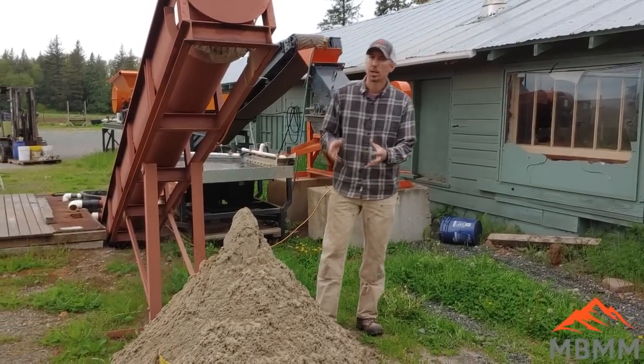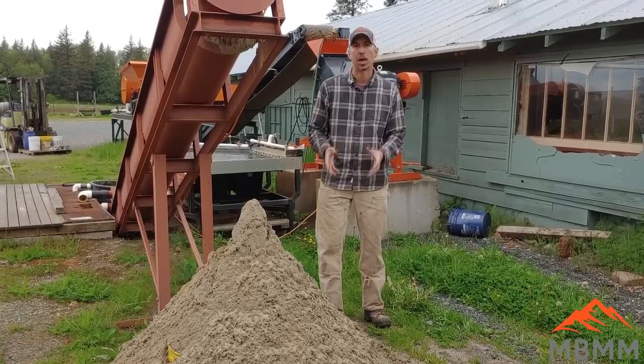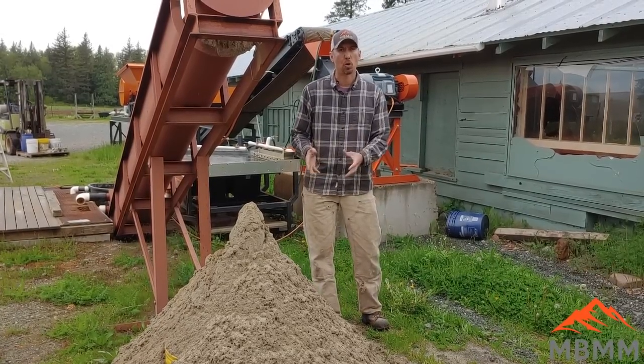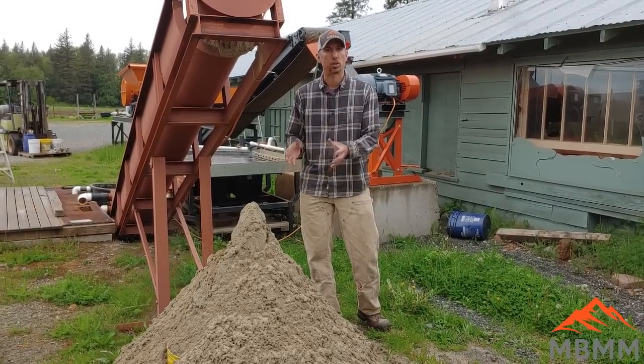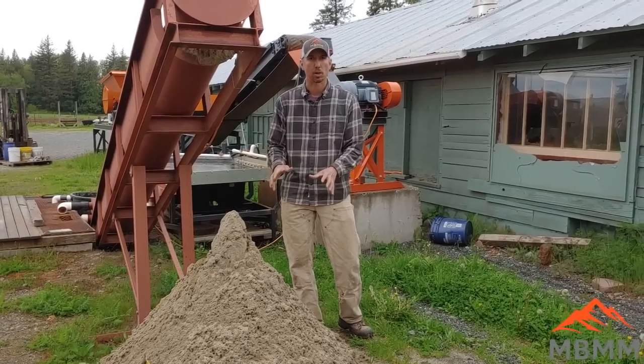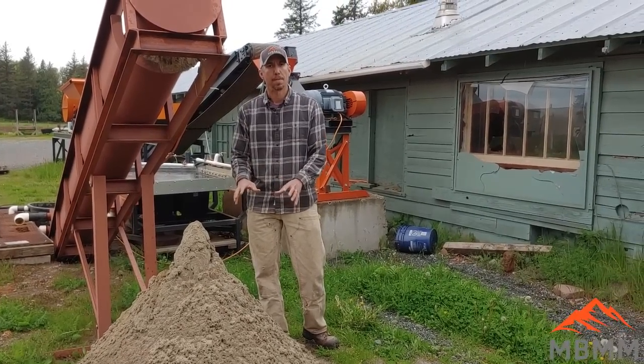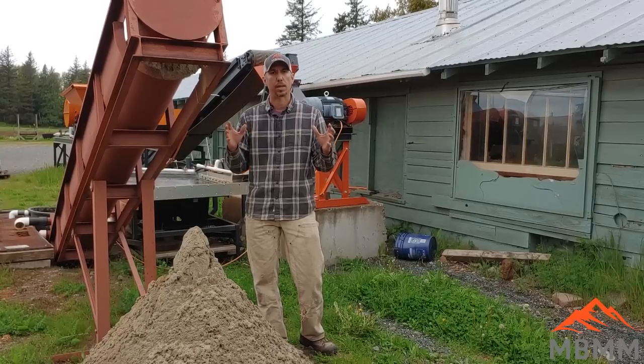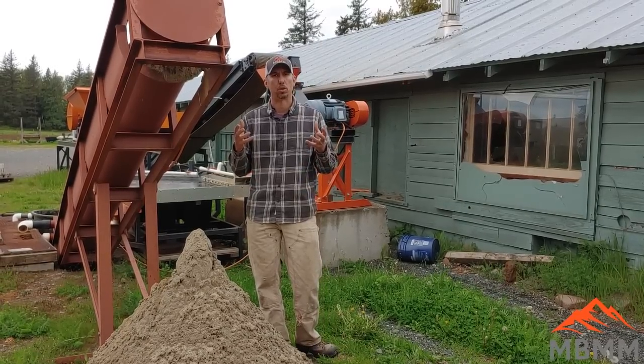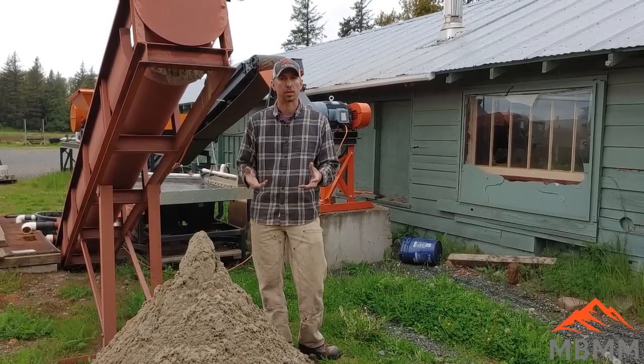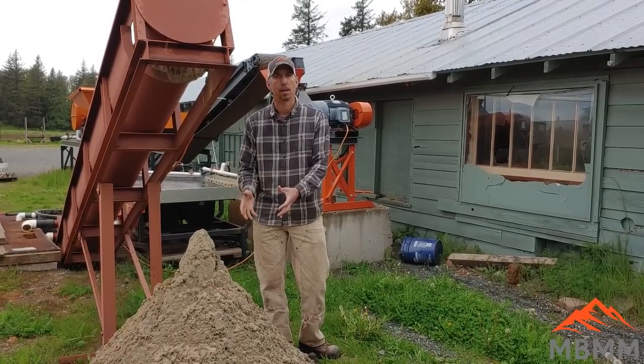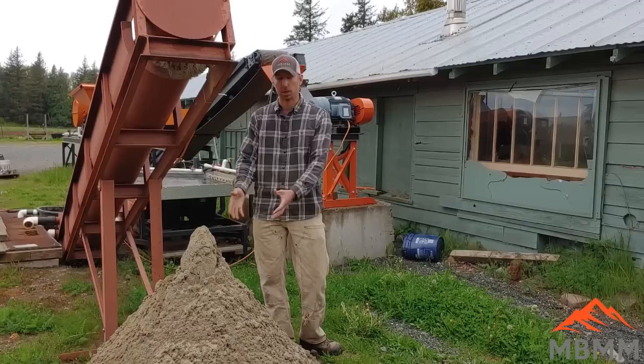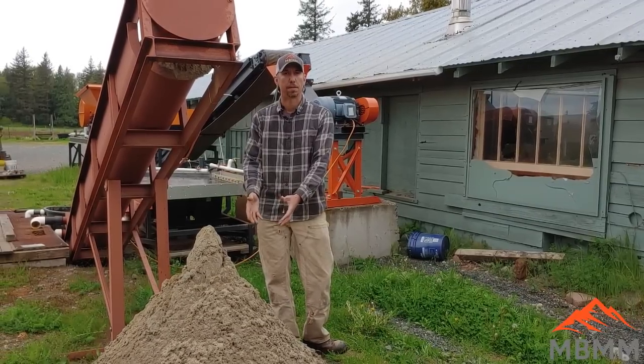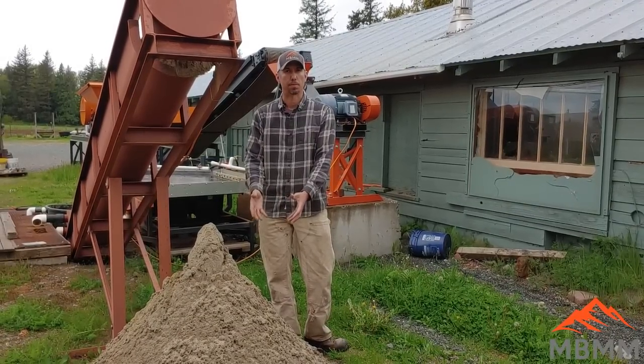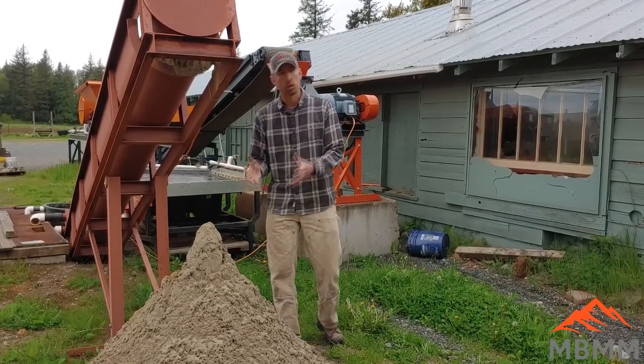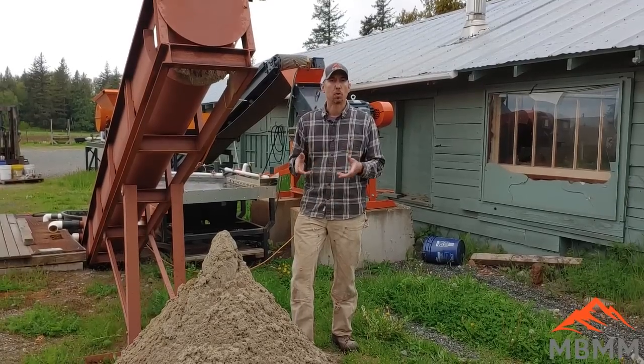This has somewhere in the 3 to 4 grams per ton of gold as it sits. And so you don't want to throw that away. We haven't lost any gold. The value is still there. And so as you get your capital up, or you're starting to produce a profit and get some money, you can take this pile and recover the gold out of it. Because there's about $100 to $150 worth of recoverable gold a ton here, and you don't want to throw that away. And that's where a ball mill comes in.